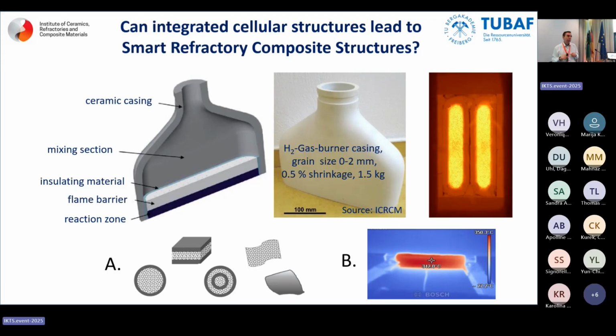With pores or with micro cracks that I can create, I can improve the thermal shock performance, but especially if I need a pure material, for instance alumina, if I want to have a gas burner, not so high temperatures in means of 2000, 3000, but in the range of H2, hydrogen firing, then I need pure alumina, and I have to get an improved thermal shock performance. So on the one hand, yes, micro cracks. On the other hand, can I integrate heating elements in my gas burner in order to improve? Because thermal gradient means thermal conductivity. It means heating from inside to outside.